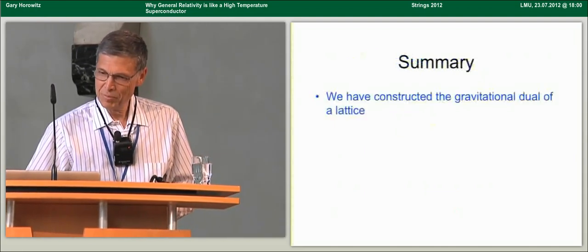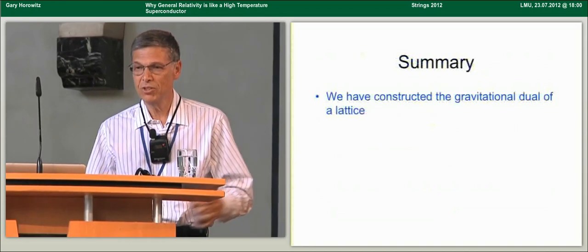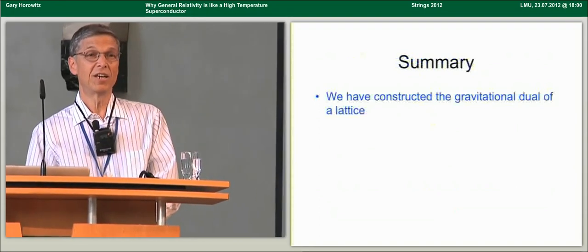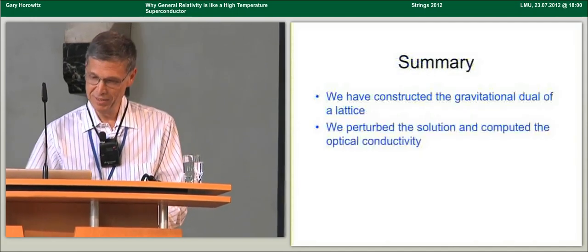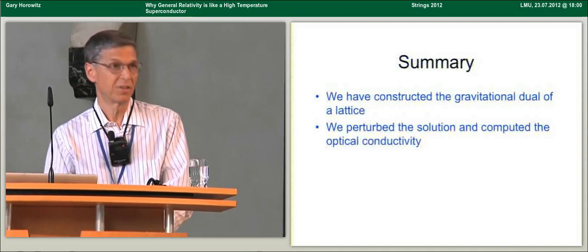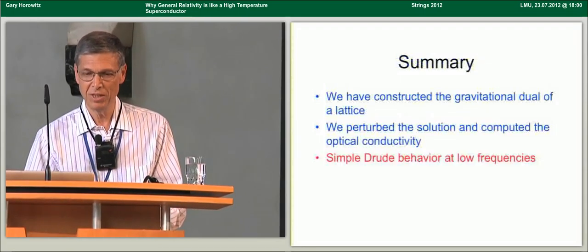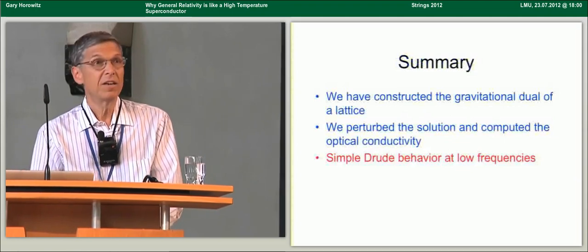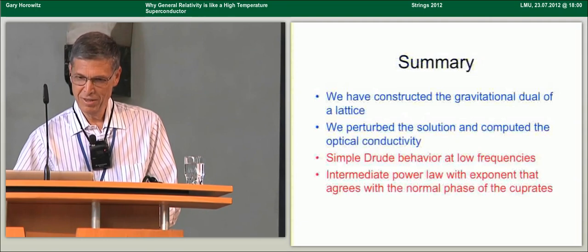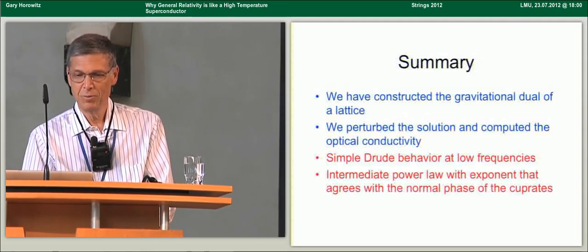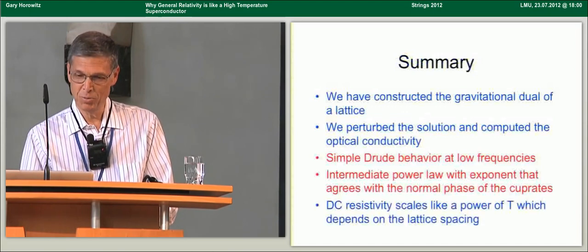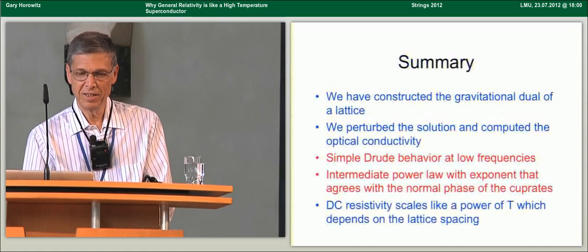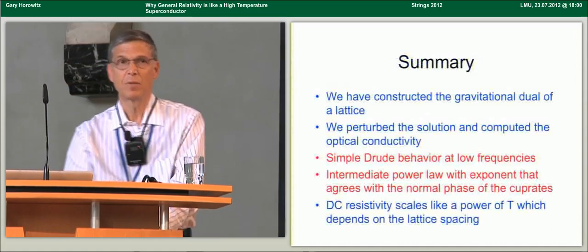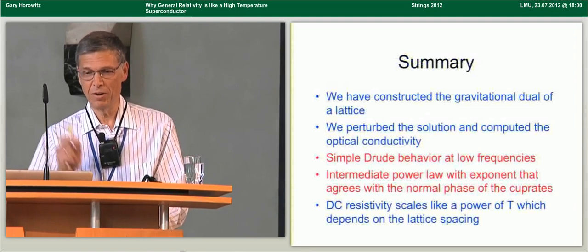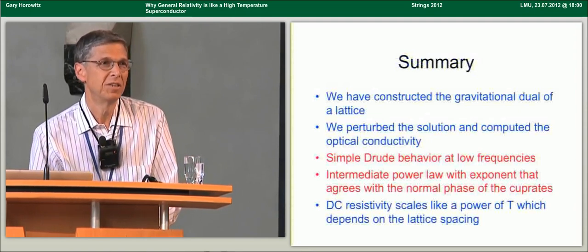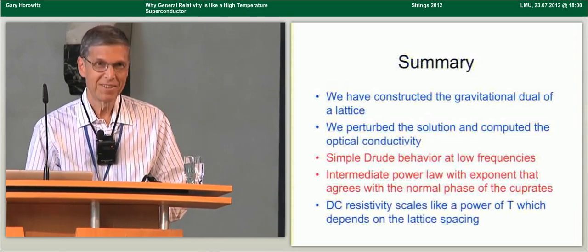Okay, so let me summarize. We've constructed the gravitational dual of a lattice. We've actually done it for 2 different lattices, and this is fully back-reacted in general relativity. We perturbed the black hole solutions and computed the optical conductivity. We found a simple Drude behavior at low frequencies, and then a transition to this intermediate power law with an exponent that agrees with the normal phase of the cuprates. Finally, we calculated the DC resistivity and found that it scales like a power of the temperature, but the power depends on the lattice spacing, in good agreement with the analysis of Hartnoll and Hofman. And I'll stop there. Thank you.